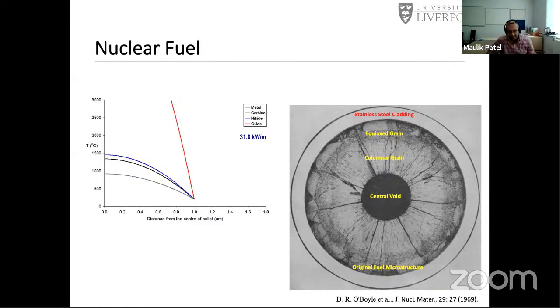So in this case, the mobile species in uranium dioxide is the oxygen. So the oxygens move. There is that porosity. Fuels have an inherent porosity. People make fuels with a known porosity because certain fission fragments, like gases, they want the gases to be accumulated at the top of the fuel rod, which is called a plenum. So there's a small spacer at the very top of most of the fuel rods, which basically helps in accumulating all the gases that are being evolved as fission products.